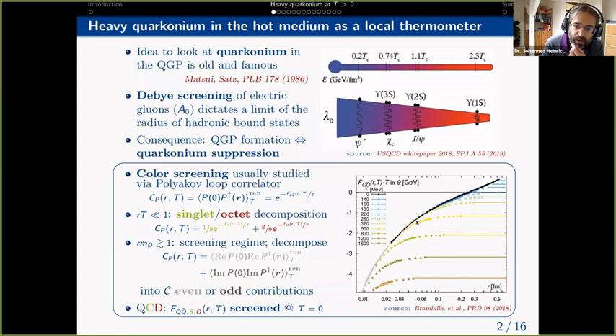What you see in this plot is, in black, the zero temperature static energy on the lattice, continued here to very small distances. This color-averaged free energy obtained from the Polyakov loop correlator approaches this zero temperature result at very small distances, where there should not be much medium effects, but then very rapidly flattens off and just assumes a constant value. And this happens for all temperatures that we have considered.